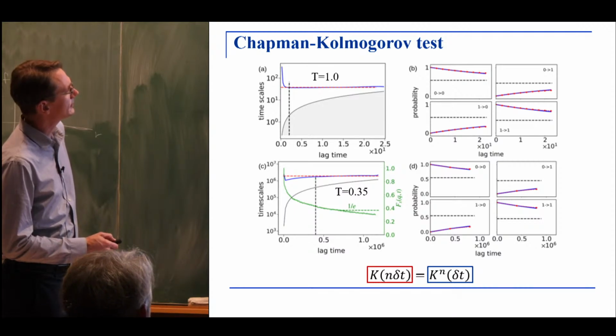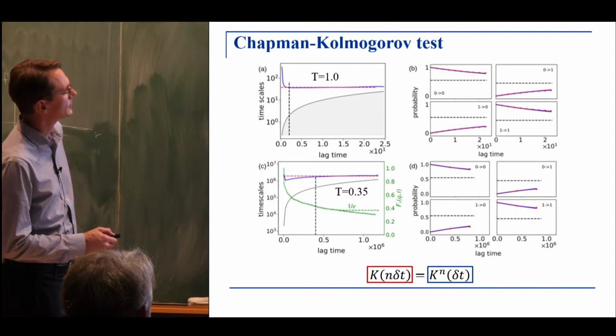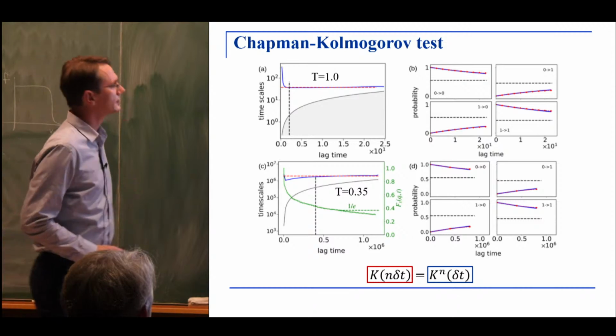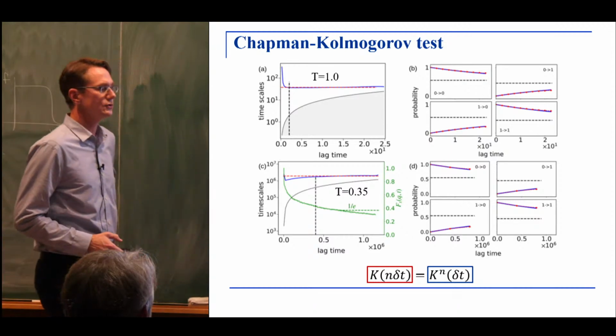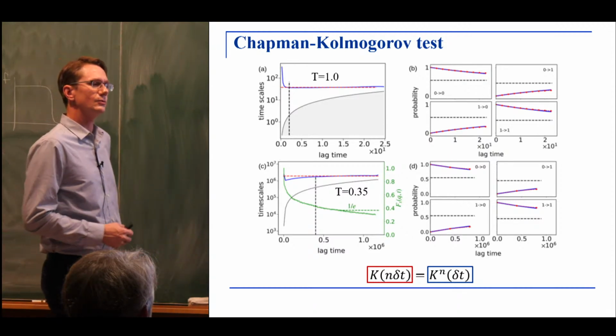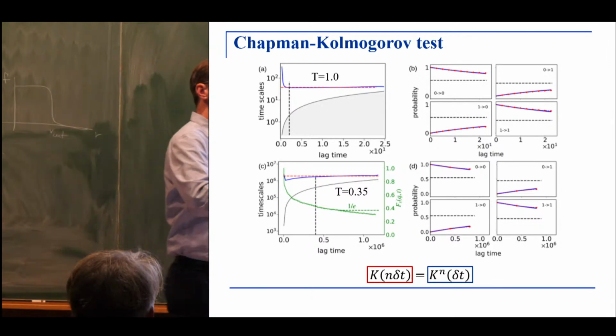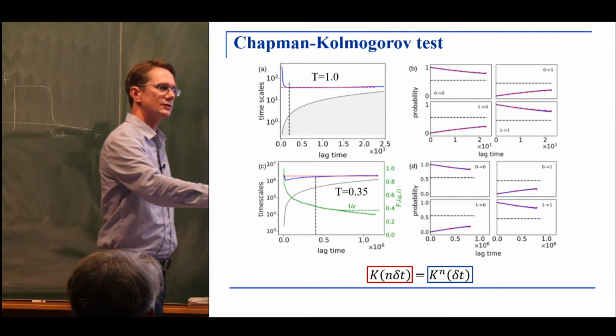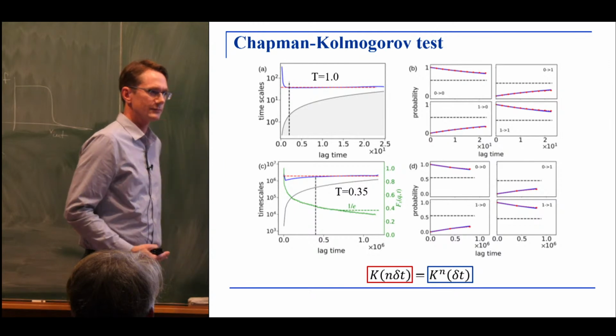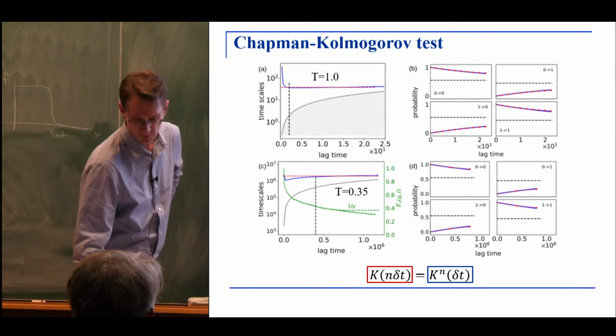You can see here simultaneously the decay of the self-intermediate scattering function, and the crossover occurs roughly at the relaxation time, but certainly not later. So we can get a memoryless dynamics if we coarse grain to a time scale that's just a bit less than the alpha time. Does that answer your question, Andrea? So this is what happens in this system here.